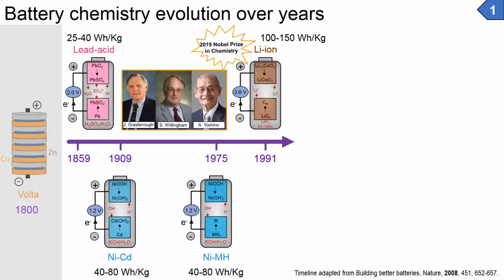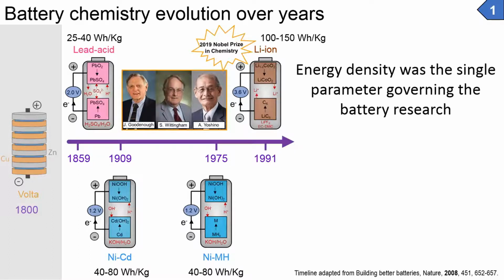So as you can see, in 1859, the energy density of the battery was like 25 to 40 watt-hour per kilogram. And then it kept growing until 1991, with an energy density value close to 100 to 150. So you can see that the single parameter governing the development and evolution of battery technology was the energy density. Well, it's still the energy density, but now we have two other parameters that we need to take into consideration for battery research.